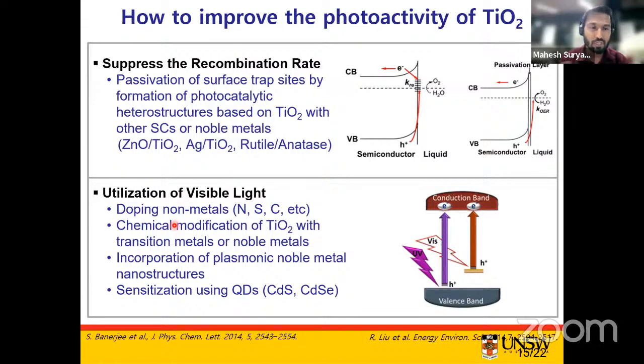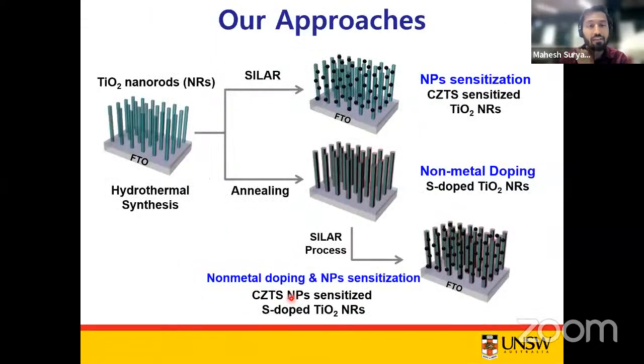So we can improve the performance of TiO2 by utilizing the visible light region, simply by doping with non-metals such as nitrogen, sulfur, or carbon, or by chemically modifying it with transition metals or noble metals. Also, by incorporating plasmonic noble metals such as platinum, iridium, silver, or gold, or by sensitizing with visible light absorbing nanocrystals, quantum dots, or nanoparticles such as CdTe, CdS, and CdSe, and there are many more actually. But we are focusing on developing earth abundant and non-toxic compounds, which we will see in the next slides.